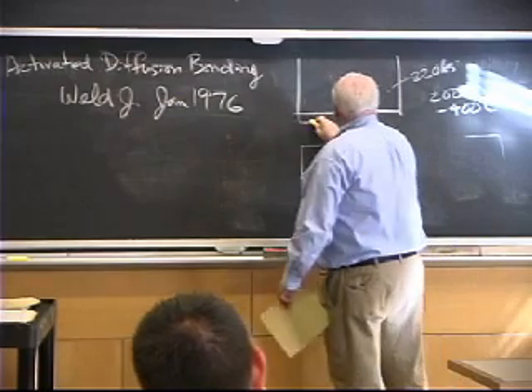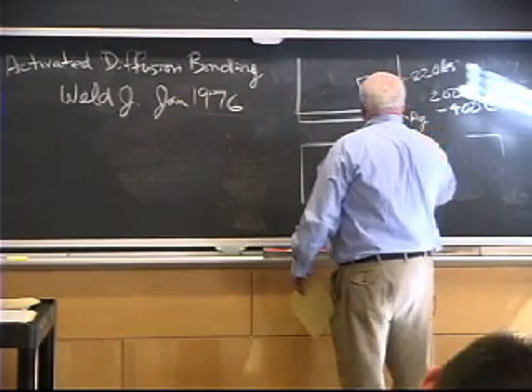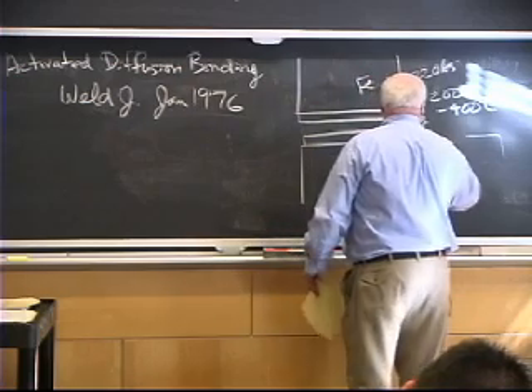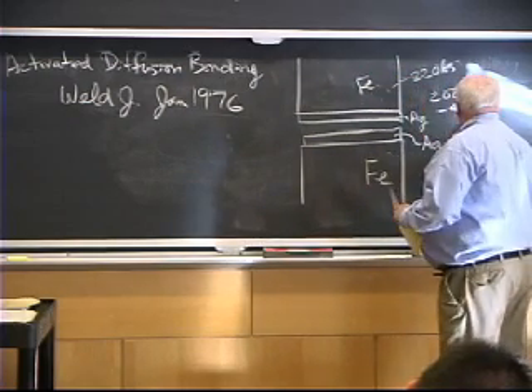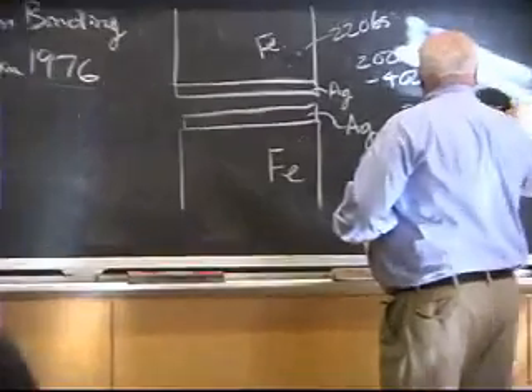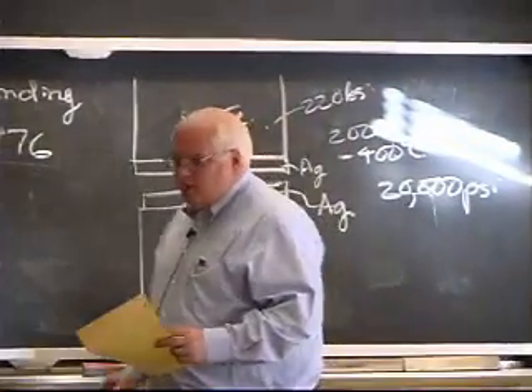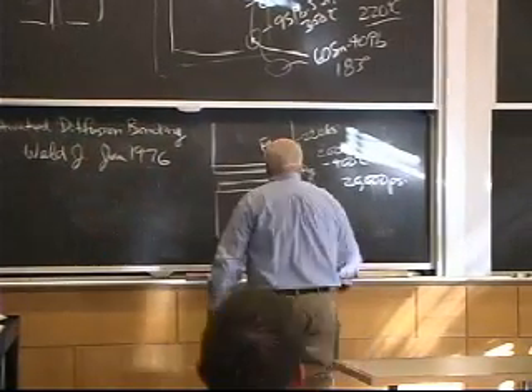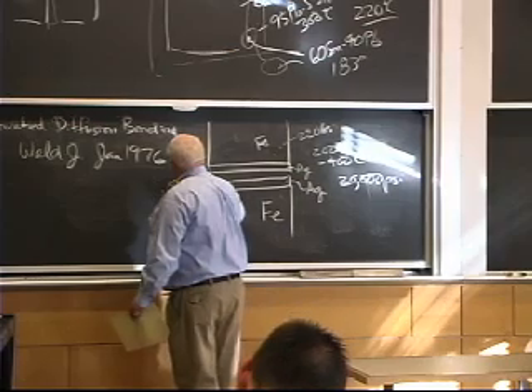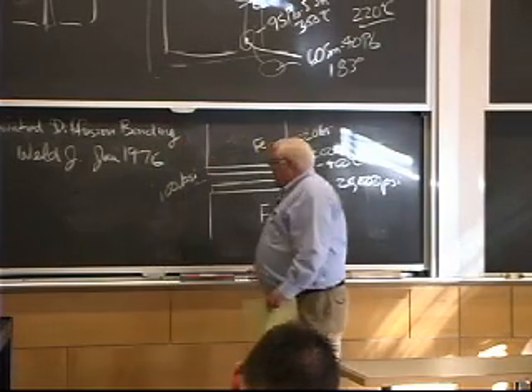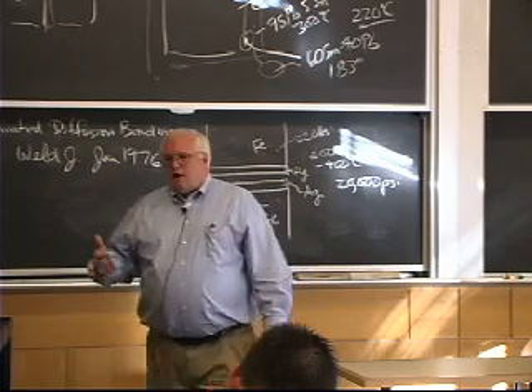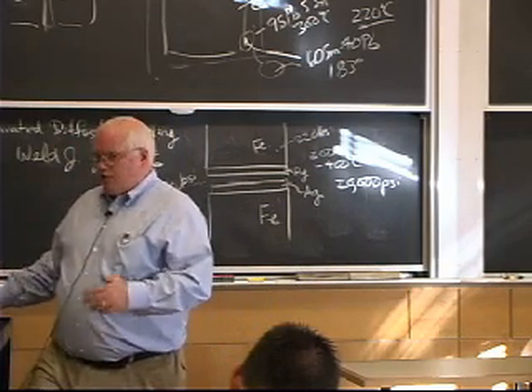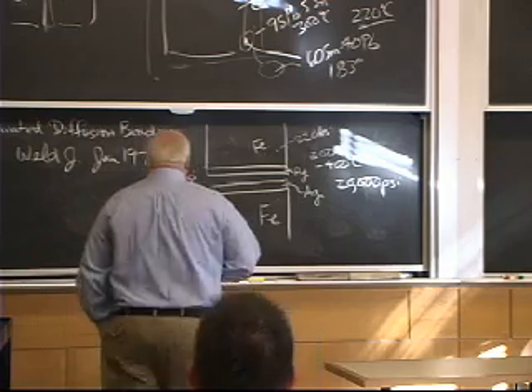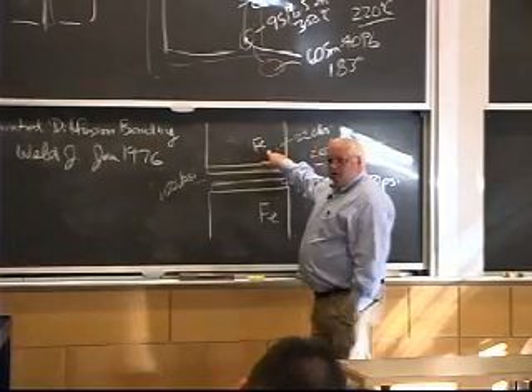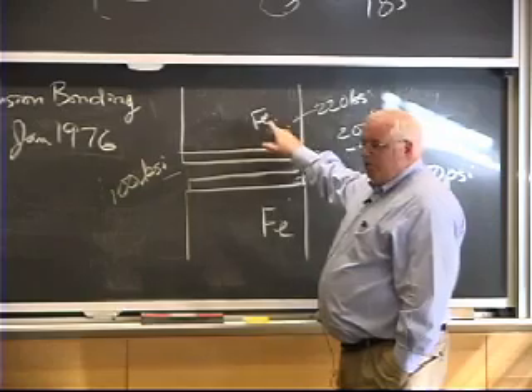They ended up plating this with silver. And they ended up using 20 KSI, 20,000 PSI, at 200 to 400 degrees centigrade. And they ended up getting joints that had 100 KSI tensile strength. Now the base iron had about 220 KSI. And there's another phenomenon going on here called contact strengthening, which we're going to talk about when we get to brazing. But nonetheless, iron is a problem because it forms an oxide at 400 degrees C. The iron oxide is so stable, you're not going to diffuse it away.